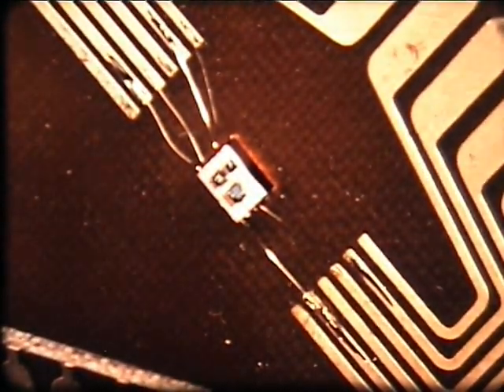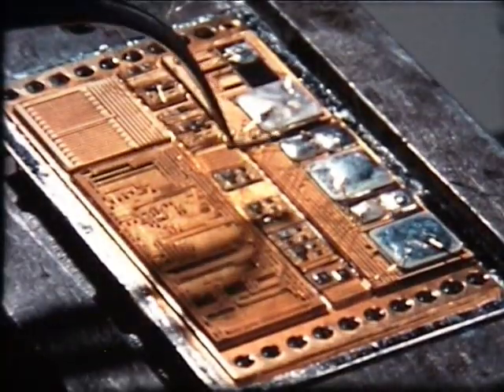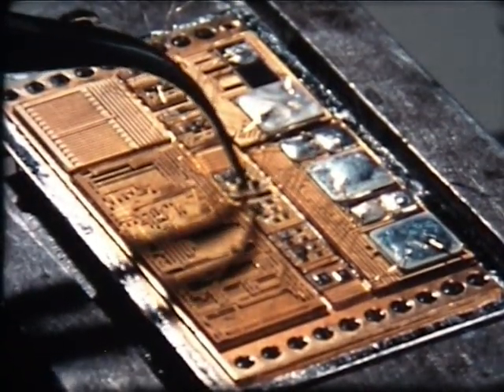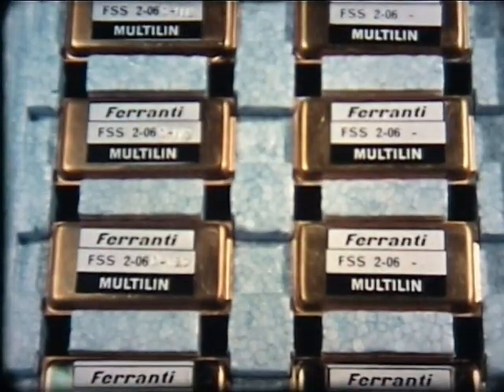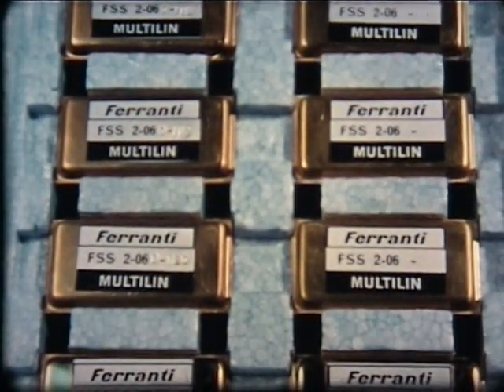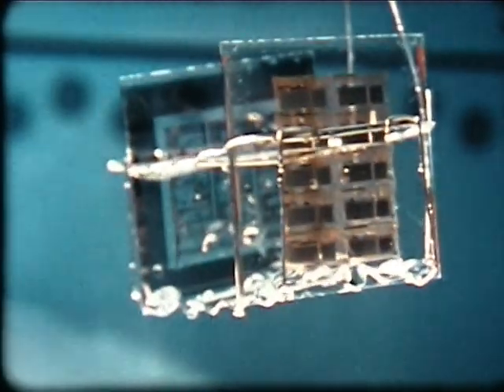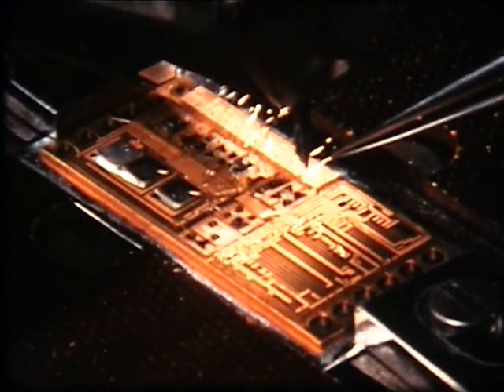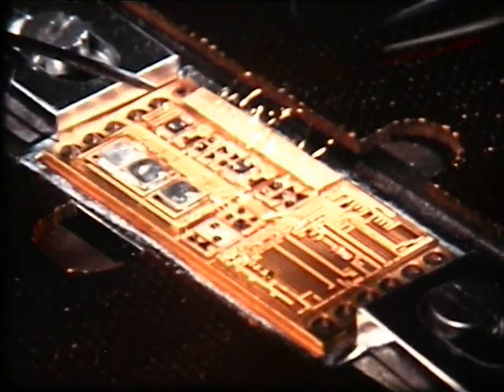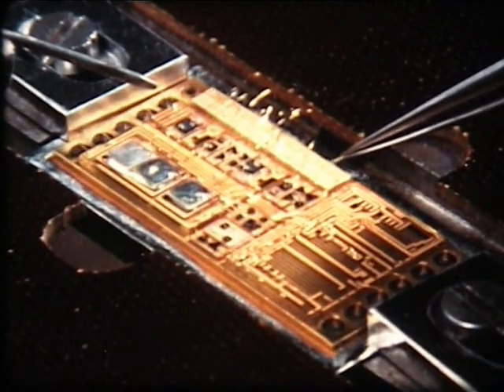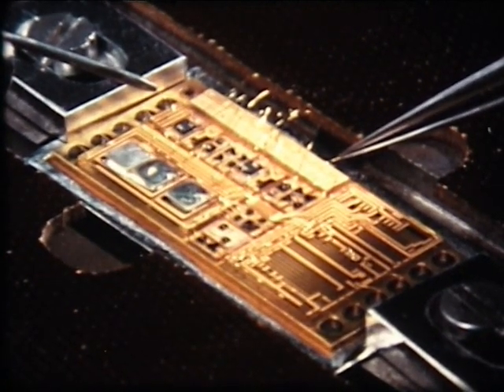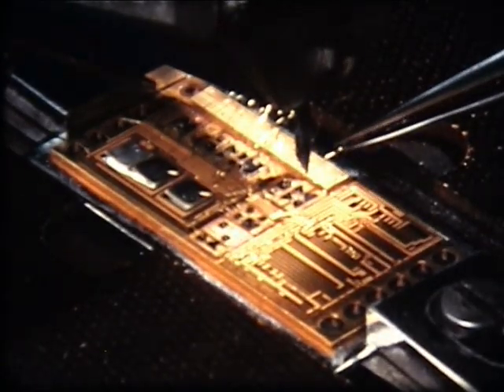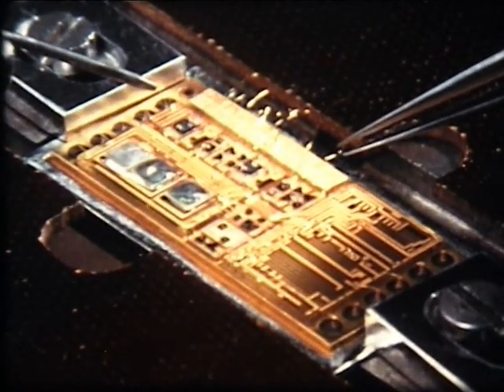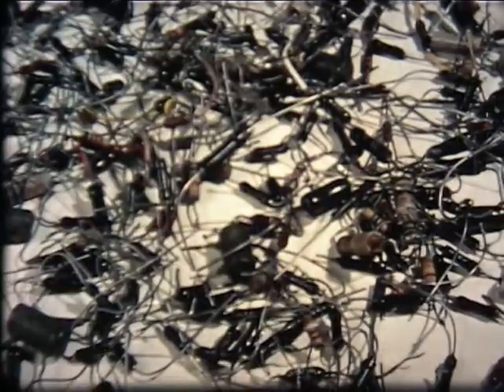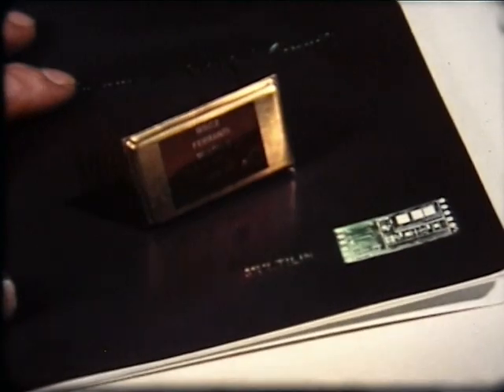For some applications, silicon integrated circuits are combined with thin film circuits, as in the multilin range of hybrid units made by Ferranti at Bracknell. Thin film resistor, conductor and capacitor patterns are selectively etched in metal films on glass. The silicon chips are mounted on ceramic substrates to ensure good heat dissipation. The assembly is interconnected using thermocompression bonded gold wire, giving a unit of extremely high package density and great reliability. 200 conventional components can be replaced by one multilin unit.